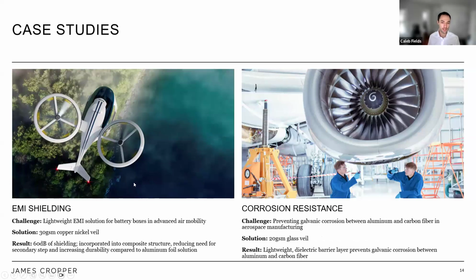So another application, as Mark mentioned, is EMI shielding, and our lightweight metal coated materials have been used extensively for EMI shielding, both in avionics enclosures actively, as well as in EMI shielding for battery boxes, both in aviation as well as automotive. So we had a customer who was looking for a lightweight shielding solution for a battery box on an electric plane. And current EMI shielding solutions are typically aluminum foil or conductive coatings. Both of these are added after the composite part is made, so it requires a secondary step. And since they're on the surface of the composite, they're less durable, so they can be torn if they're in contact with something that's abrasive.